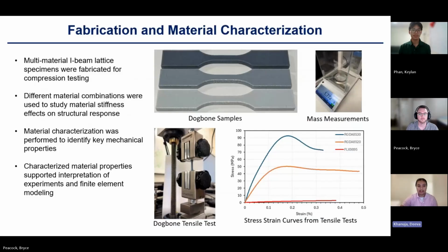Fabrication and material characterization. Multi-material I-beam lattice specimens were fabricated for compression testing. Different material combinations were then used to study material stiffness effects on structural response. Material characterization was performed to identify key mechanical properties. Characterized material properties supported interpretation of experiments and finite element modeling. As shown on the right, we printed the dog-bone samples, measured their mass, performed tensile tests on them, and then processed the data to achieve these stress-strain curves.